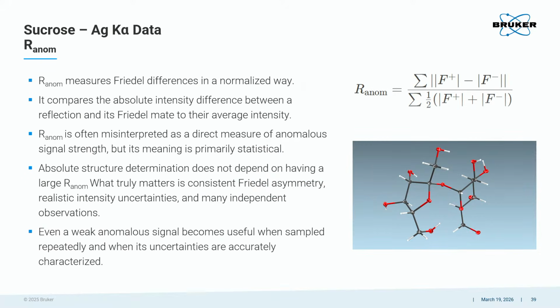So when we look at R_anom, that sort of explains why this is possible. It measures the Friedel differences in a normalized way, where it compares the absolute intensity difference between a reflection and its Friedel mate to their average intensity. Basically, resonance scattering is typically when you have a plane, it doesn't matter whether it gets diffracted from this side or this side, but if you have a non-symmetric structure, for certain reflections this is not true anymore. And that minute difference in intensities is used to determine the absolute configuration.